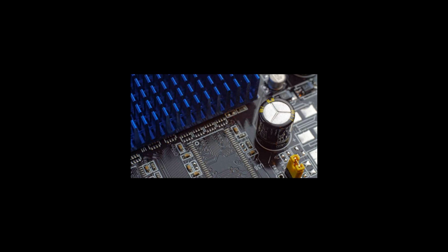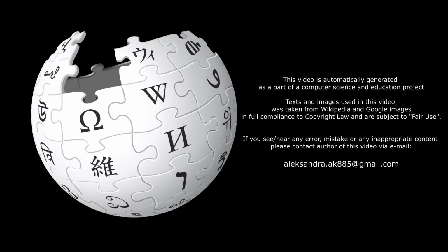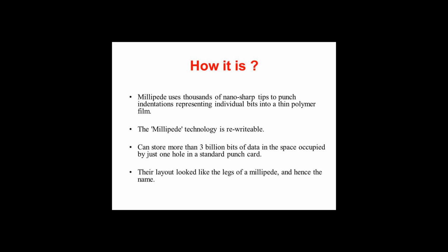To accomplish a read, the probe tip is heated to around 300 degrees Celsius and moved in proximity to the data sled. If the probe is located over a pit, the cantilever will push it into the hole, increasing the surface area in contact with the sled, and in turn increasing the cooling as heat leaks into the sled from the probe. In the case where there is no pit at that location, only the very tip of the probe remains in contact with the sled, and the heat leaks away more slowly.